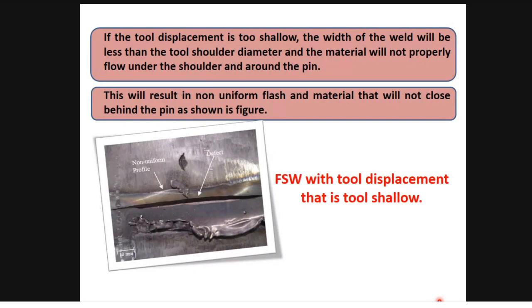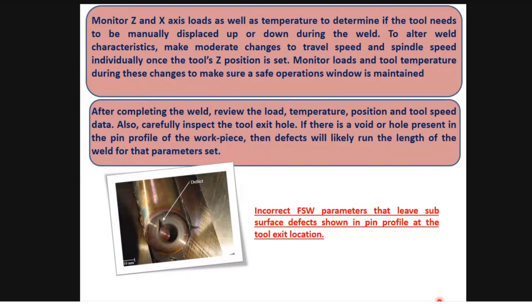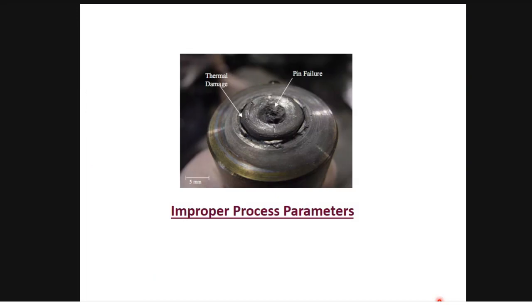And you see that if you use an improper tool displacement, that is if the tool displacement is too shallow, the width of the weld will be less than the tool shoulder diameter, and the material will not properly flow under the shoulder and around the pin. This will result in non-uniform flash and material that will not close behind the pin, as shown in the figure. Incorrect parameters also leave subsurface defects near the exit hole of the weld. With improper process parameters the shoulder can also get thermal damage, and sometimes the pin also fails. So the failure will occur in the pin.